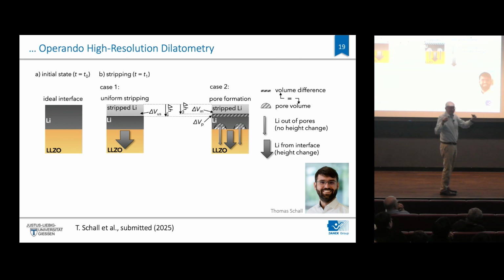And if you have a metal piece, and if it really is being dissolved layer by layer, you get, of course, a continuous thickness change. If pores are being created, well, you don't see that in the outer length of your electrode, right? So making a dilatometric experiment with a nanometer resolution will allow you to get that information. I have an engineer in my group who was very good in setting up this dilatometric experiment, and we managed, in fact, to measure that.